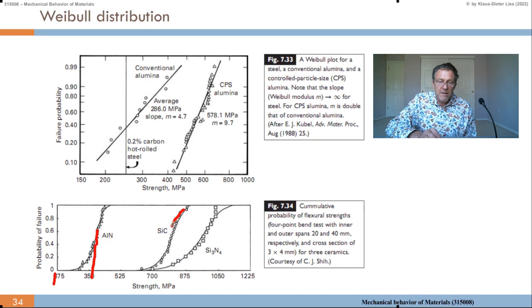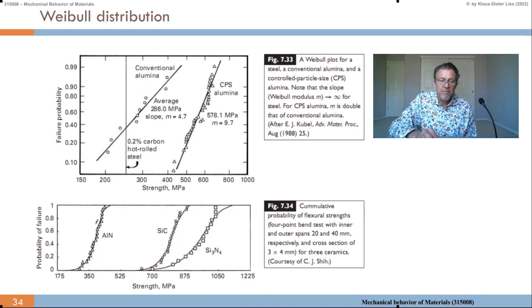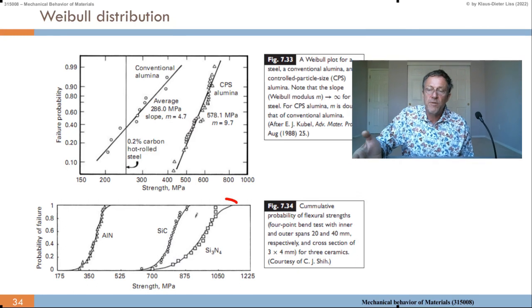Silicon carbide also is relatively steep. If we look to silicon nitride, it's less steep, so it has a larger distribution. However, of course, the sigma zeros is different for the 3 types of materials. These are direct material properties. Also, what this shows, the data, they fit well the Weibull distribution in the 2 cases, aluminum nitride, silicon carbide. In silicon nitride, it fits very well up to here, probability of failure 80%, and then it deviates a bit. So that's probably either the statistics is not good enough or the model may need to have some modification due to properties of the materials. We did many assumptions.